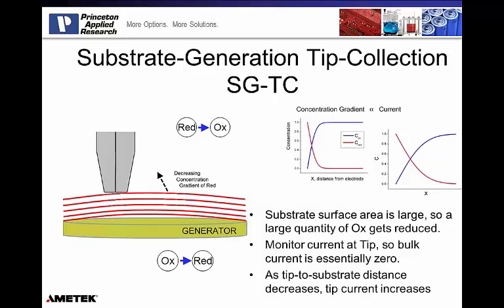I put an oxidizing potential, plus 650 millivolts, on the tip. Remember, no electrochemistry happens on the 3+ iron at plus 650 millivolts. But if the iron 2+ comes in contact with a platinum wire that's been polarized to 650 millivolts, I now cause the oxidation of iron 2+ back to iron 3+, and current flows.